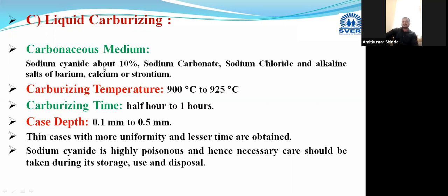Here, in liquid carburizing, the generally used carbonaceous medium contains 10% sodium cyanide. In addition to this, sodium carbonate, sodium chloride, and some alkaline salts of barium, calcium, or strontium are used. The generally used carburizing temperature is 900 to 925 degrees Celsius, and carburizing time is 30 minutes to 1 hour, and very thin cases can be achieved here with very high uniformity.